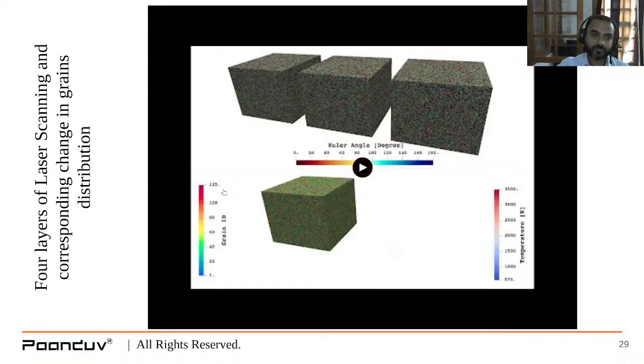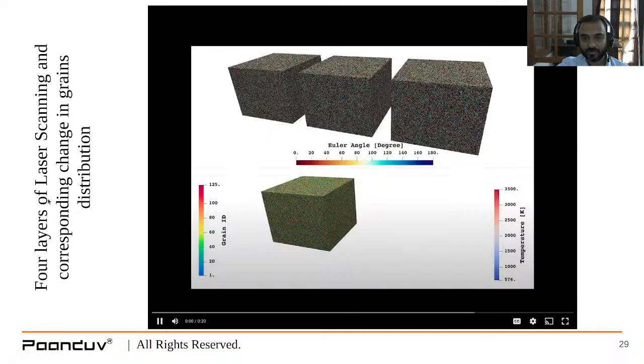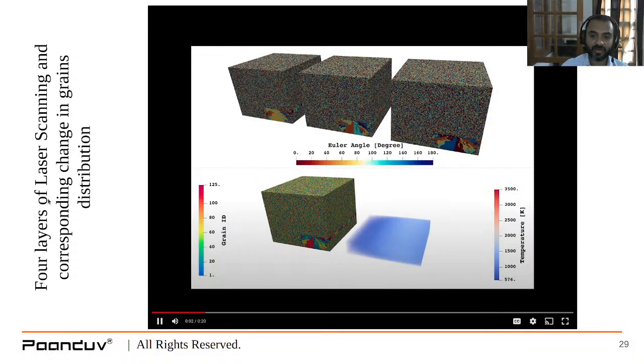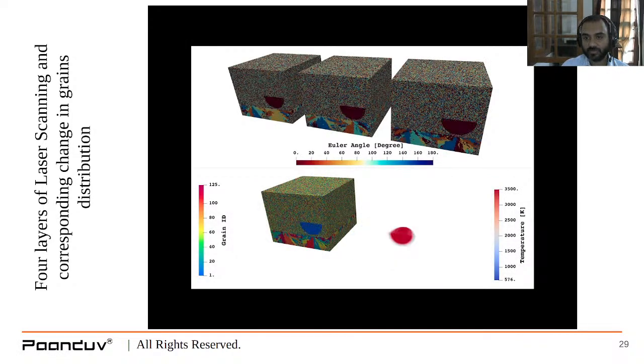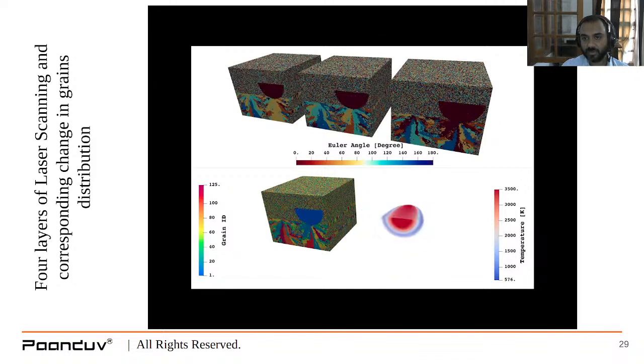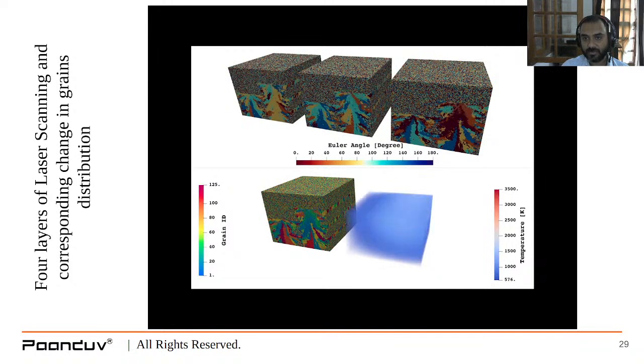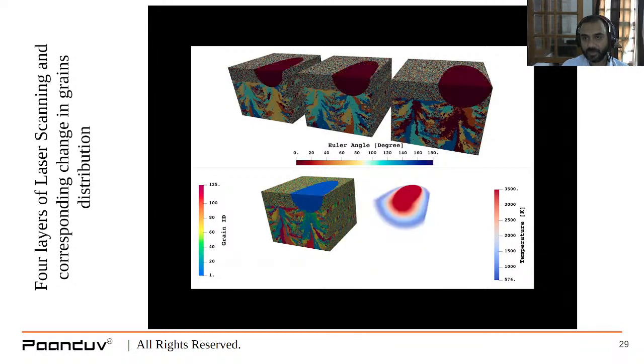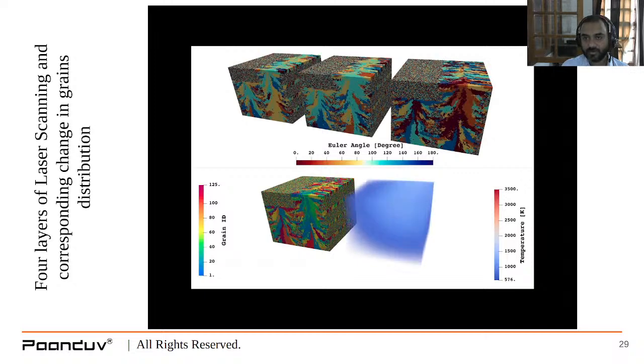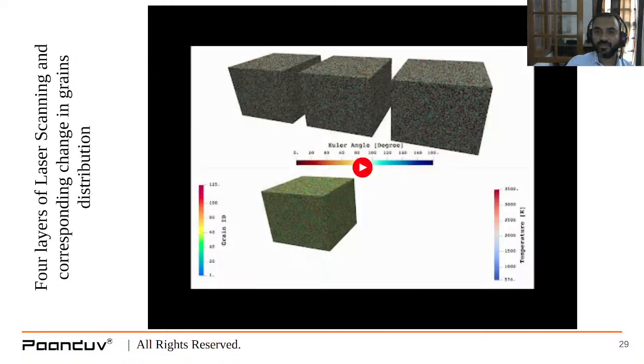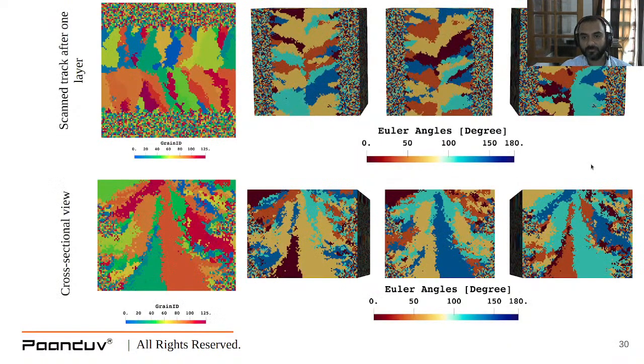So what exactly we do in this sort of modeling using AM PravaH, I'm going to show 4 layers of laser scanning and corresponding changes in grain size distribution. You can see in the beginning all the grains are randomly oriented. So layer 1 is track 2, layer 2 track 1, track 2, and then layer 3 track 1, and then track 2. Then if we go to layer 4, we have track 1 and track 2. So at the end of this whole process, you can see the grains have completely misoriented, and we are able to capture different, we are able to visualize.